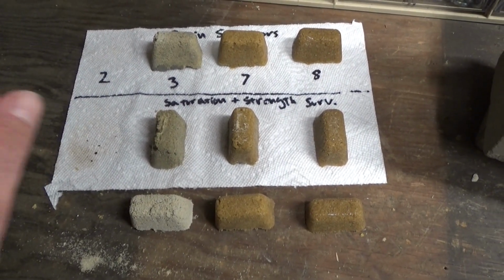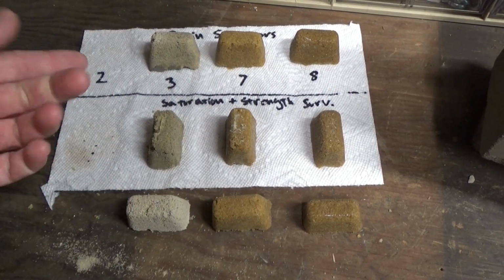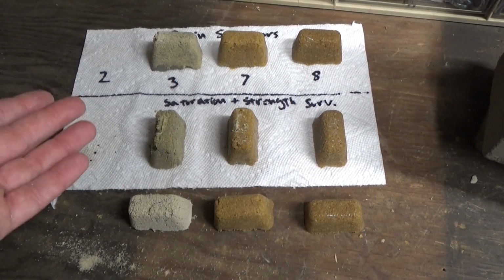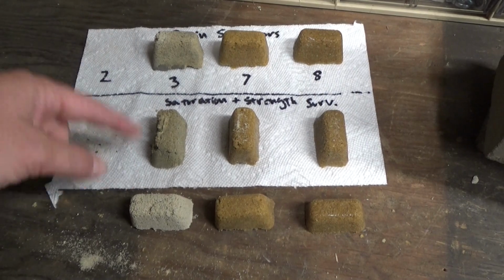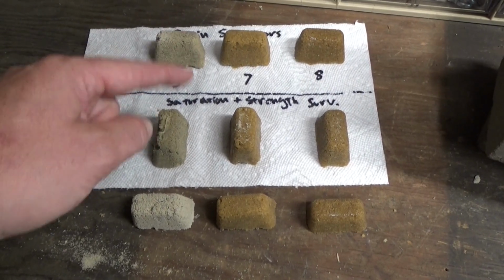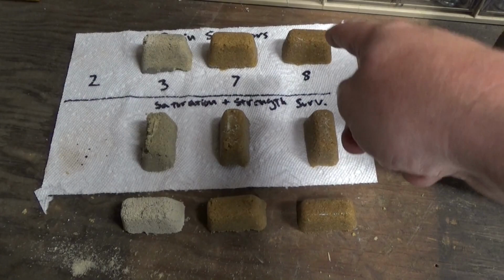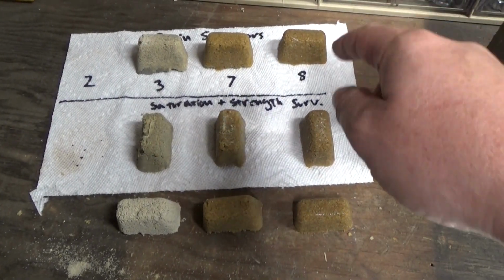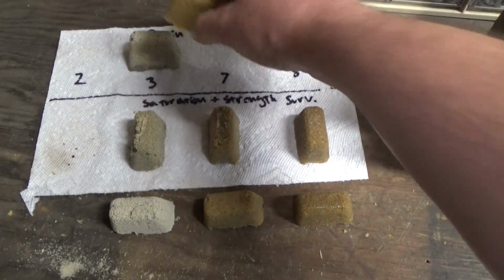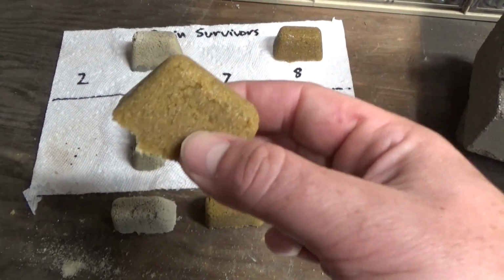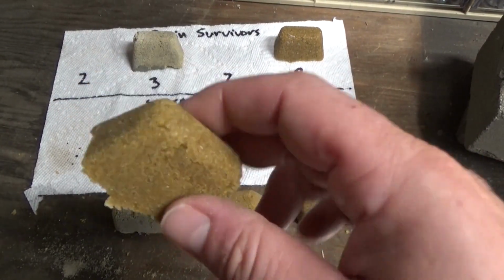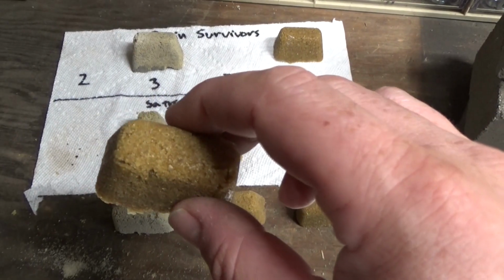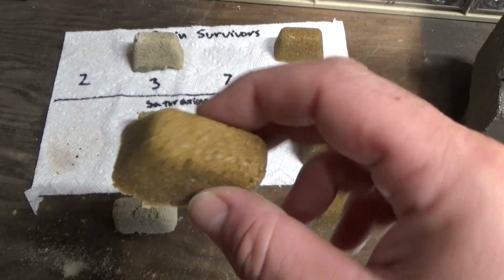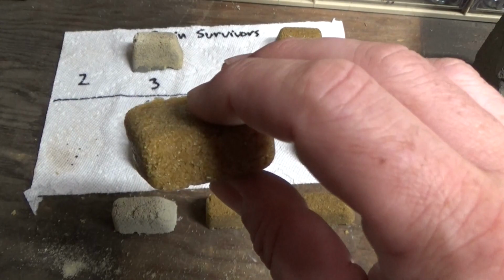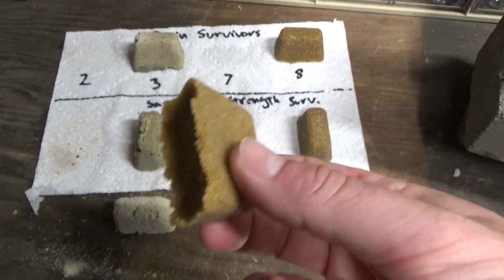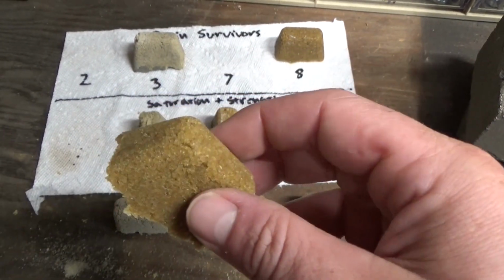So that leaves Portland cement, which you'd kind of suspect because cement plus sand is basically concrete, so this is pretty strong. 100% silicone plus sand works really well. And then number 8, our 2-part epoxy sand works really well. I would like to note that the silicone kind of looks the best from an appearance standpoint. This looks pretty close to what the raw sand looks like. So if I was going to make a 3D sand sculpture, I would probably use 100% silicone to mix in and then sculpt it and let it set up.